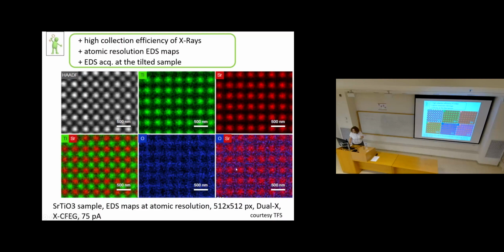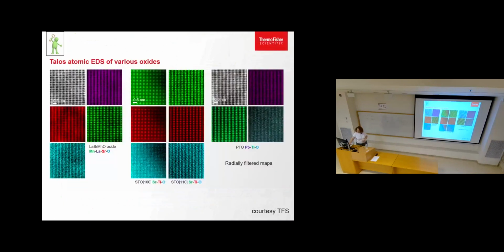And if you take a look at this map, this is the map of oxygen. So this is our third way to image the light elements at atomic resolution. So after exit wave reconstruction and iDPC contrast, we also have this EDS ability. I would say our previous ability was nothing as compared to these results. And here you have a few more examples of mapping different compound oxides at atomic resolution with EDS. Okay.